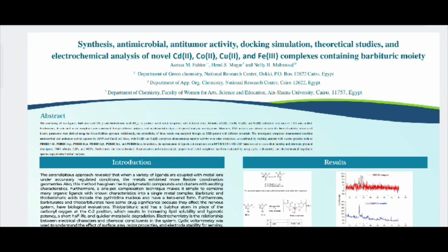Furthermore, the obtained mixed complexes were confirmed through different analyses such as elemental analysis and spectral analysis investigations. Moreover, TGA analysis was utilized to study the thermal stability, whereas all kinetic parameters were derived using the Coats-Redfern approach. Additionally, the crystallinity of these metals was analyzed through XRD patterns with different potentials. The investigated complexes demonstrated excellent antimicrobial and anti-tumor activity against two different cell lines, with cobalt and copper complexes demonstrating superior activity over other complexes, as confirmed by docking analysis.